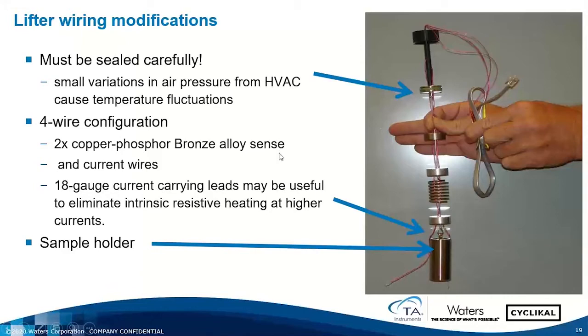What I mean by that is, for example, the 4-wire configuration can compensate for the voltage drop down the wires, but those wires are also going to carry current. And if your current is high enough, the wires themselves can start to produce thermal power and then result in an extraneous source of thermal power that's not coming from your battery. And we'll show you how to determine that. And the sample, again, as I said, is placed inside the stainless steel ampule.